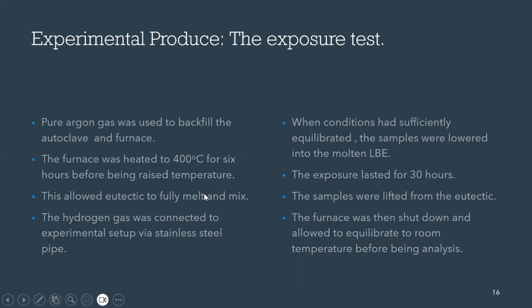So the hydrogen was connected to the experimental cell via stainless steel pipe. And after that, when the conditions had sufficiently equilibrated, the samples were lowered into molten LBE. For this part, the exposure lasted for 30 hours. After that the samples were lifted from the LBE, the furnace was shut down and allowed to equilibrate in temperature before being analyzed.